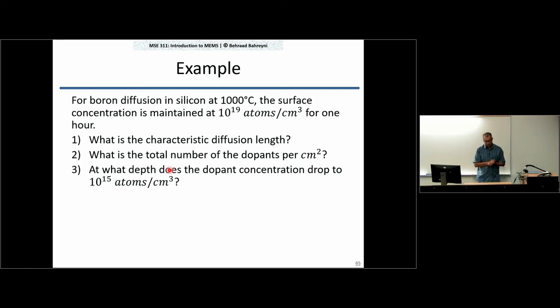Now, the second question is, what is the total number of dopants per centimeter squared? So again, we go back to the formulas that we had, and we have this CS, I need to read it off here, 2 square root of Dt over square root of pi. Then if you plug in the values, you have all the numbers you need. CS was 10 to the 19 atoms per centimeter cubed, and with the square root of Dt we just calculated, we get this value. So this is 8.4 times 10 to the 13 atoms per centimeter squared.